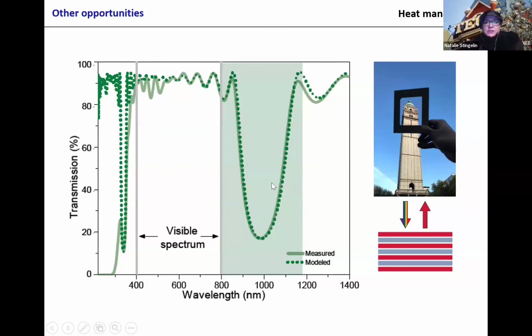So how can we shift it to the infrared? As mentioned, we can make thicker layers. If we make the red and blue layers thicker, this band will shift to the infrared. In principle, we can simply make thicker layers, getting to 1 micron thick. This one I think was 150 nanometers for the hybrid layer, so you can go easily to 300 nanometers.